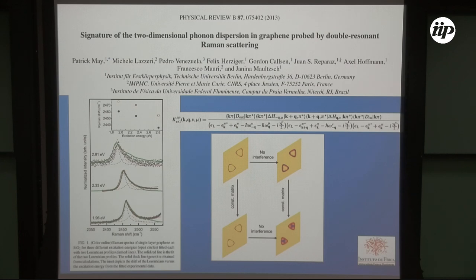And in the end of the process, I will sum these numbers in our Brillouin zone, and then I will square that to get a real number, and this will be the Raman intensity. But when I'm calculating, I have quantum phases that can interfere. I can very easily in the calculation turn off the quantum interference. I can just, instead of summing the complex number, take the modulus of the numbers and then sum them. In this way, I can theoretically turn off the quantum interference.